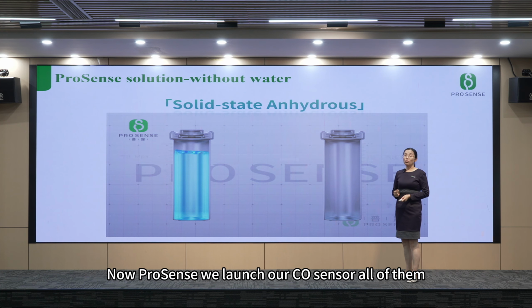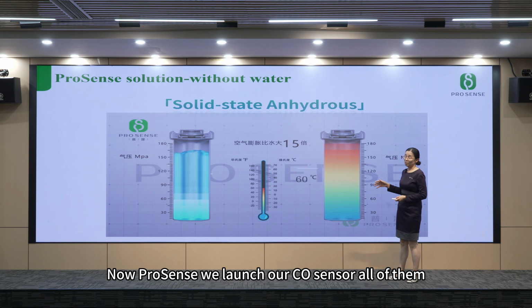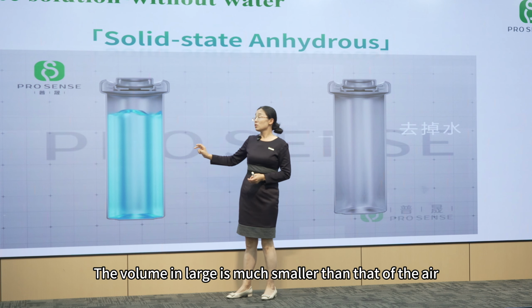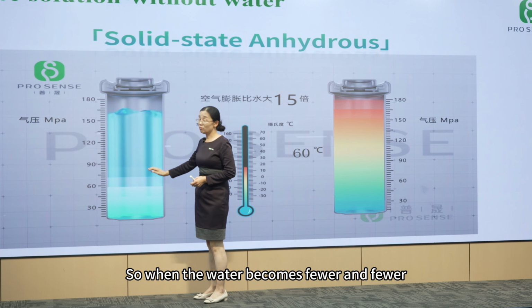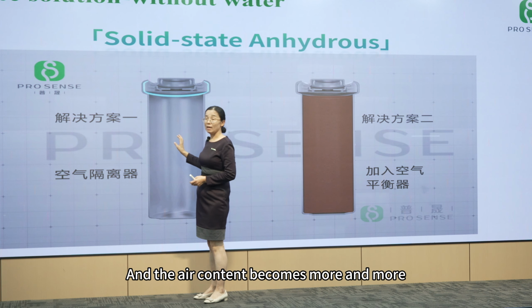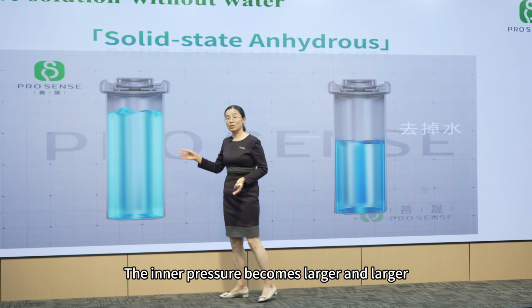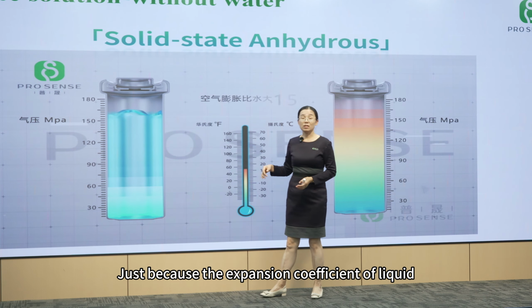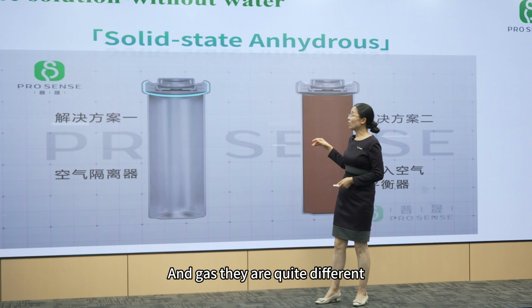Now, at ProSense, we launch our CO sensors, all of them without water. Why? Because we found a phenomenon by chance: as the water becomes less and less, the air content in the tank becomes more and more. We all know that for the same temperature change, the volume expansion of water or liquid is much smaller than that of air. So when the water becomes less and the air content becomes more, the inner pressure becomes larger and larger, just because the expansion coefficients of liquid and gas are quite different.